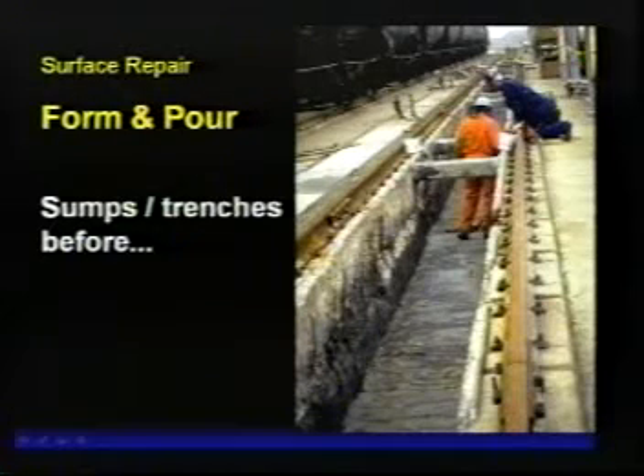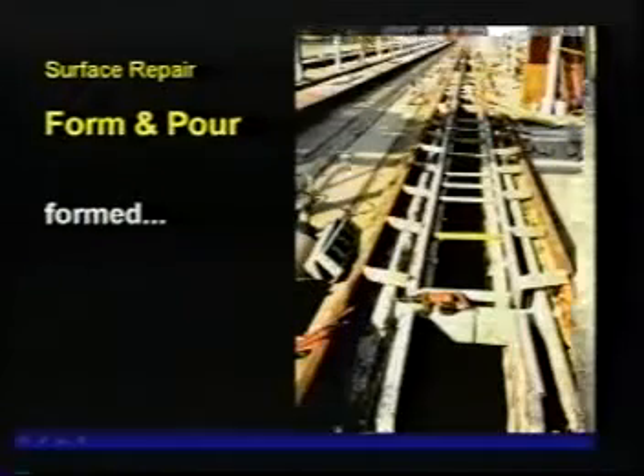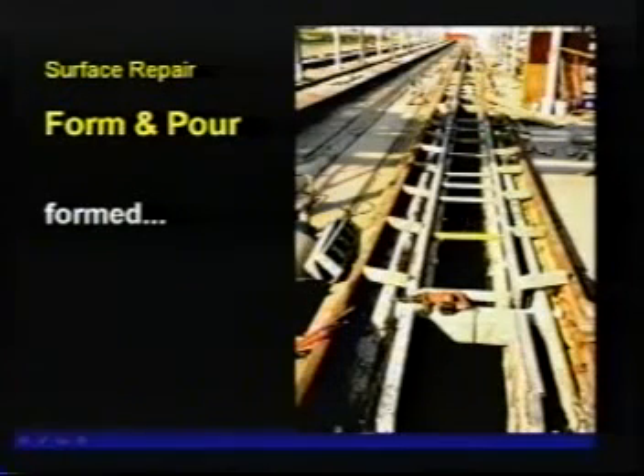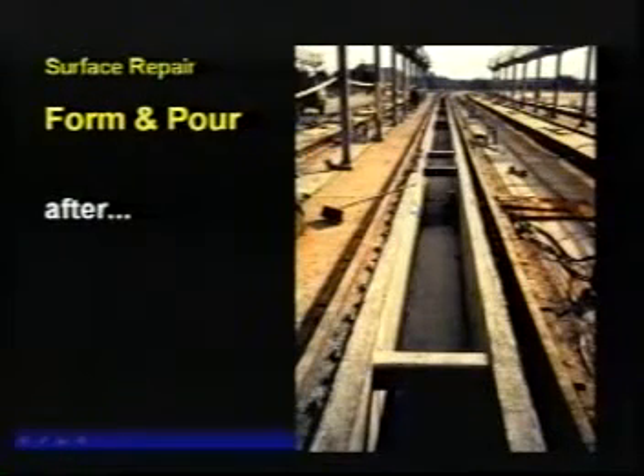This is one-sided forms. In this particular job, this is a sulfur trench where rail cars dump molten sulfur in this trench, and then it moves down the trench into another area. The molten sulfur has attacked the concrete, and it requires repair. So the method of repair here is to build a trench within the trench. You can see the formwork. This is one-sided formwork, and there's a gap here between the formwork and the existing concrete. And this is what it looks like. In this particular case, a silica fume concrete was used for its density and resistance to the same deterioration mechanism that the original concrete went through from the exposure to the molten sulfur.